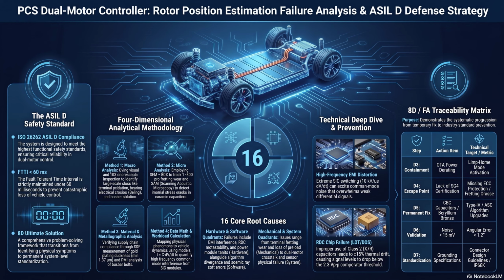Okay, Dimension 4, sensor physics and sealing, brings us back to the mechanical defenses. To stop the EDM microlightning from blasting craters into the motor bearings, they integrate a carbon brush shaft grounding ring, or SGR. It is such an elegantly simple tribological solution to a really complex electromagnetic problem. The highly conductive carbon filaments physically ride on the spinning motor shaft, providing a direct, ultra-low impedance path to the ground casing. By continuously bleeding off the induced capacitive charge, the shaft voltage never reaches the dielectric breakdown threshold of the lubricating oil. Right. The Townsend avalanche is entirely suppressed. No plasma, no fluting. Brilliant.